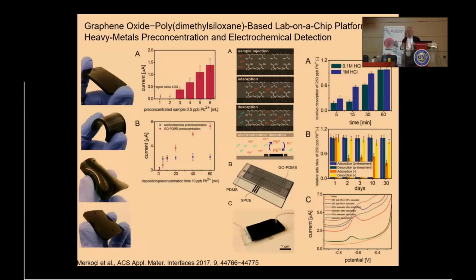Or by using these chips with in situ removal, not only detection but also removal, we were able also to detect heavy metals. So by using again graphene oxide, polydimethylsiloxane chip, and using some electrodes, we were able to detect some heavy metals by applying electrochemical stripping analysis, and at the same time taking advantage of the chemistry of this composite, the biocomposite, which is flexible to remove the contaminants. So these heavy metals.